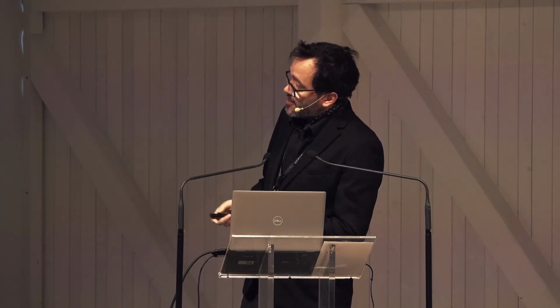representing in a simplified fashion the real complexity of a slurry, where you already have a problem of scales, because you have anode material particles which are extremely large, micrometer scale, and you have solvent molecules which are nanometer scale, right? Then you need to simplify your problem in order to simulate it. And in this model, we describe interactions, as I was mentioning before, between the different types of components that you have in the slurry.